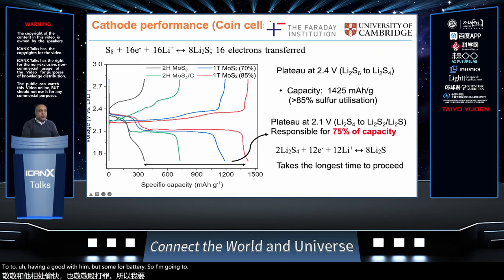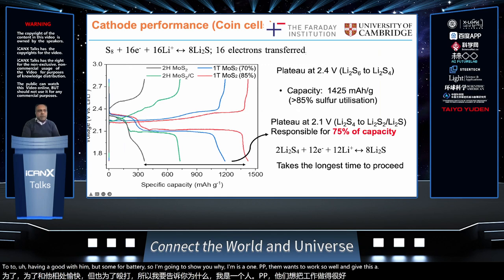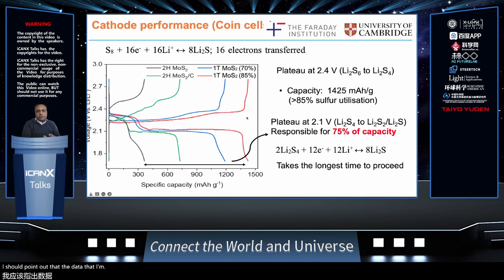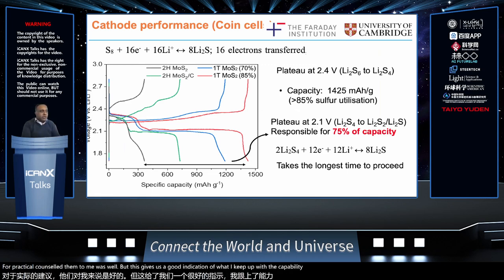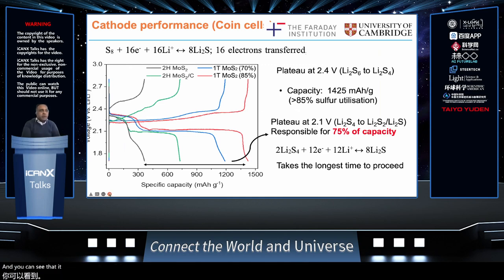So I'm going to show you why this 1T phase MoS2 works so well and gives us very high capacity. I should point out that the data that I'm showing you now in this slide are for coin cells, okay? And when you make coin cells for battery research, you typically use conditions that are most favorable for demonstrating the capabilities of your electrode materials. So I'll show you the conditions that we use for coin cells. They're not realistic, but then towards the end, I'll show you realistic conditions for practical pouch cells that we've made as well. But this gives us a good indication of what the capability of the 1T phase MoS2 is. And you can see that it's quite promising.